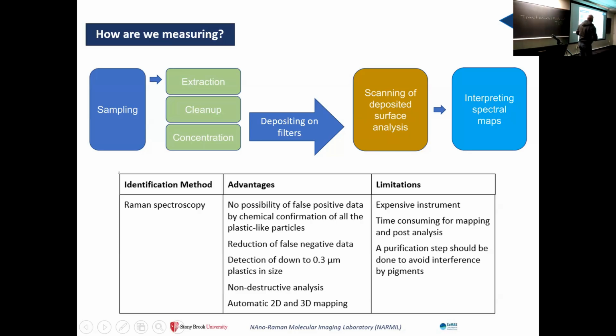Then we take these filters to our analytical method, in which we scan the surface of the filter, and we produce maps of this surface. And then we do an interpretation of these spectral maps. We do this part using Raman spectroscopy, and Raman offers a huge advantage in comparison to other methods. For example, if Raman is telling you that a particle is plastic, it's 100% plastic. There's no room for mistake on that, on false positives or